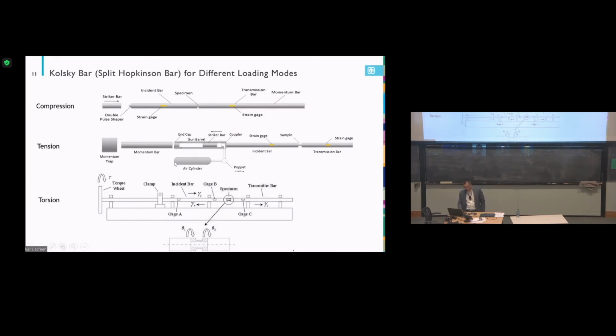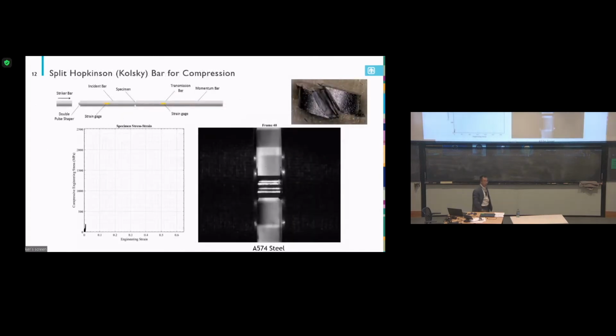And for the torsion, that's different because we are still improving the torsion version. The general practice for the torsion version is we have a long rod, we clamp one end, then apply the pre-torque here. Now we suddenly release the clamp, and the torsional wave propagates into the long rod. This is not like a gas gun or something, but I personally don't like this very much, so we are making a significant change to this version, and I have a postdoc to keep working on this. So the goal is to try to break the samples.